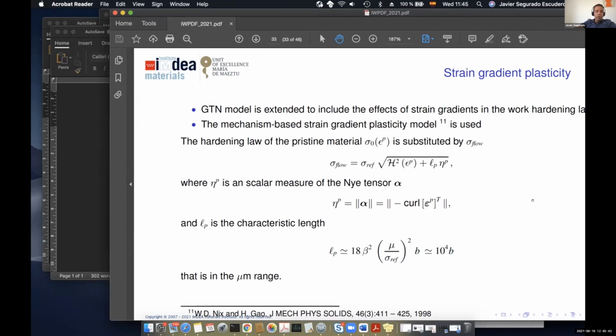Yeah, that's absolutely true. It's a good comment. I said at the beginning that the size effect in strength was clear. Smaller is stronger, but in ductility, it totally depends on the damaging mechanism. And in the case of particle fracture or decohesion, normally the size effect is just the contrary, as has been observed experimentally. The smaller particles break earlier or have a decohesion earlier.